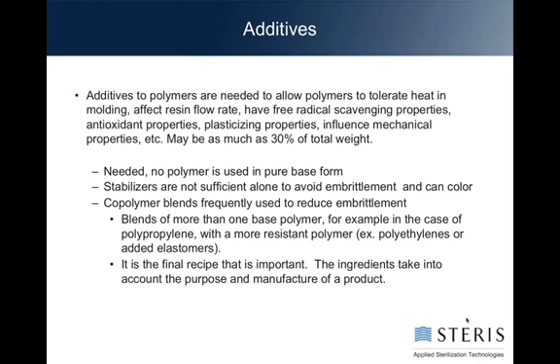They're more likely a blend of another polymer that has in its structure most likely aromatic rings, probably the benzene ring. Benzene rings are considered very stabilizing to a material that will be irradiated. So blending in things like a polyethylene or a polymer with some additional elastomeric properties, these things provide those structures that can act as a sink for a lot of those ionized particles so that they don't mess with your structure as much as they would if they were free to continue down all of the material in your system. It is always a recipe, and the final recipe is what's important.